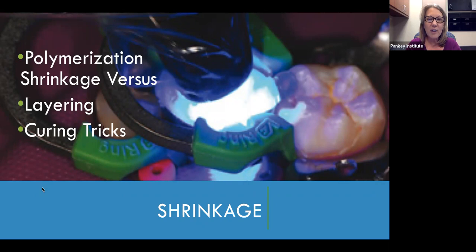What the manufacturers and scientists were able to do, by altering the chemistry of the composite — the type of filler particles, the shape of the filler particles, really reimagining the chemistry of composite — is actually impact the direction of the polymerization shrinkage. Classically, a bulk of composite shrinks right to the center, pulling away from the bonded interface. It puts stress on the marginal integrity, stresses the dentin adhesive, can decrease bond strength, increase bond degradation, and could even fracture enamel rods — really compromising the margin of the restoration, which is always the first place a restoration shows signs of aging and needs to be redone.